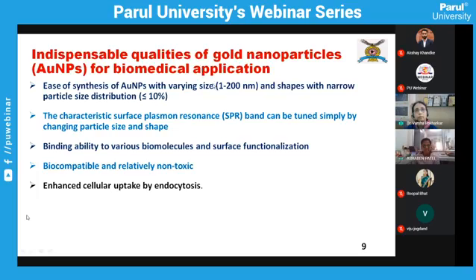So you can imagine that getting particles below 200 nanometer is such a difficult task in the case of polymeric nanoparticles or other nanocarrier systems. But with gold nanoparticles, we have a very easy route of synthesizing them in different sizes and shapes with a very narrow particle size distribution, because we are not just worried about the size, but what we are more worried about always is the size distribution of a particulate sample. So we get a very narrow size distribution in the case of gold nanoparticles.